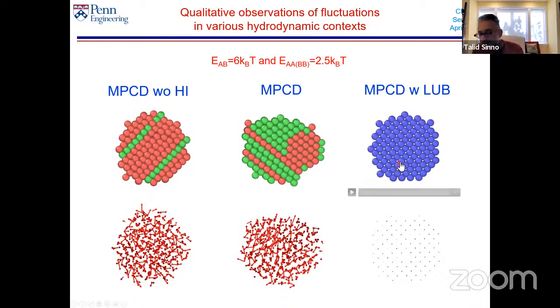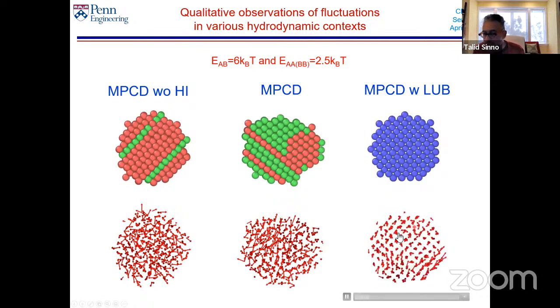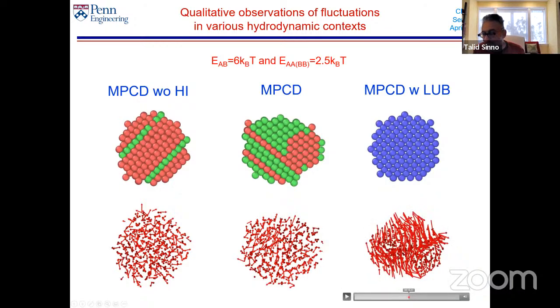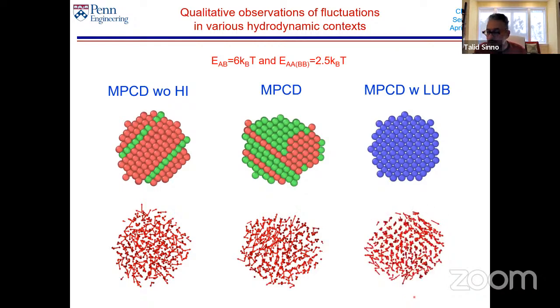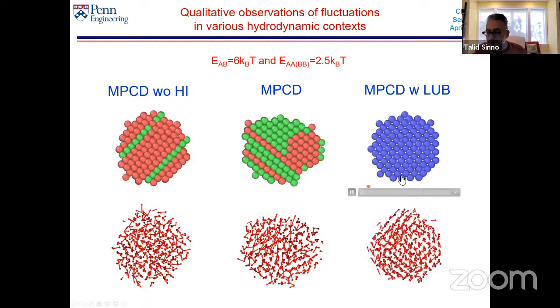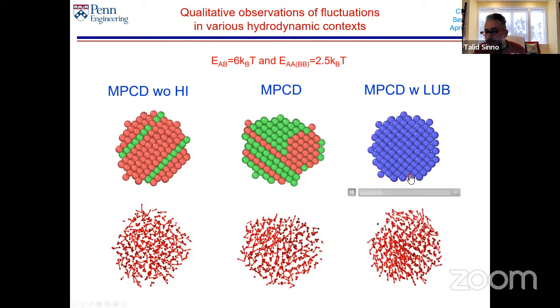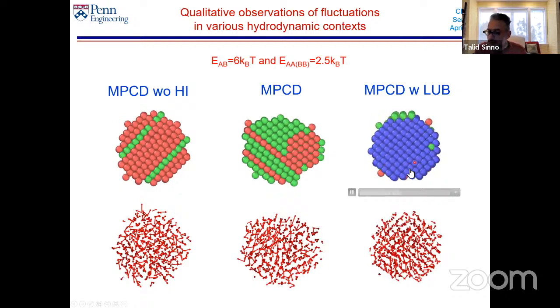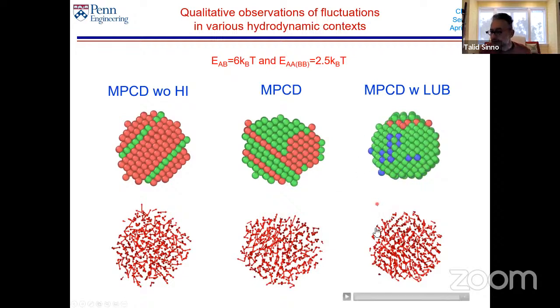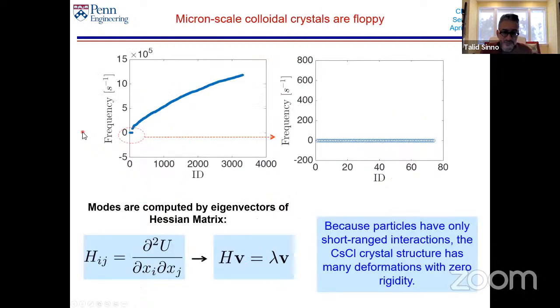And when you add short-range forces, and I'm going to emphasize these are only approximate short-range forces, you see something even more correlated. So now they become really correlated. The transformation becomes very clear, and I'll see if I can find it, yeah, so it's literally right in here. The instantaneous velocity vectors become very organized. And so this whole deformation is now taking place in a solvent controlled way. And then once it's over, then I just have small vibrations. And again, if you look at this, the particles really move much more subtly now because they're constrained by their hydrodynamic interactions. And once the transformation takes place, you get an almost complete FCC crystal, which is a lot more consistent with the experimental observations.